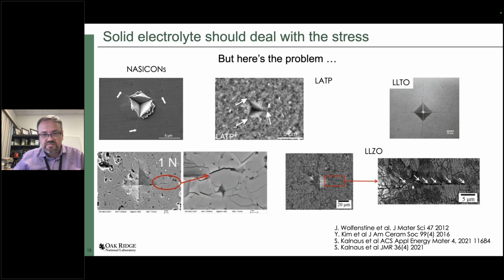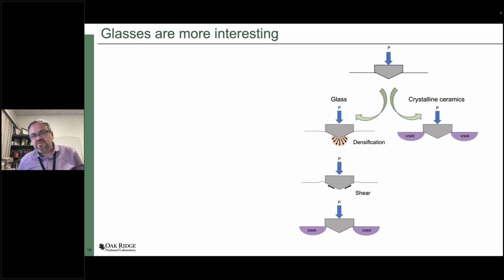And there is a relatively simple reason for that. In crystalline ceramics, the energy penalty to create dislocations is really large because of the typically large Burgers vector. So the response to the load is usually fracture because it's more energy favorable.